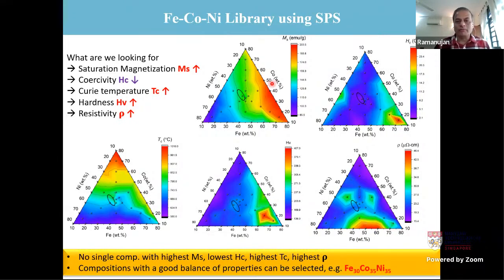Typically you want high saturation magnetization, and you can see that there are certain compositions which we have circled here, which have promising combinations of these properties. For example, you look at this ellipse here, it has reasonably good MS, low HC, medium TC. So it all depends on which properties are more important. So you can actually quantitatively decide which composition has the property set that you would like to select. For example, in this case, Fe30, cobalt 35, nickel almost equiatomic would have a reasonable balance of properties.